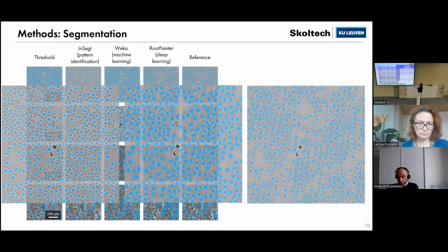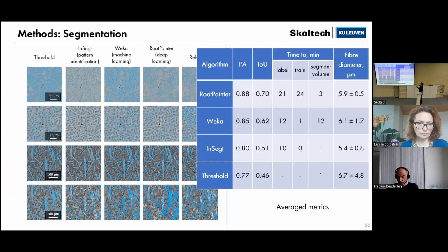And if we move to the metrics, we can see that the deep learning algorithm is best for image-related metrics. And of course, its fiber diameter is much closer to the original six microns diameter. But we have to train it, though the segmentation time is not as long as, for example, for machine learning. So it requires training, but after that it gives very good results.